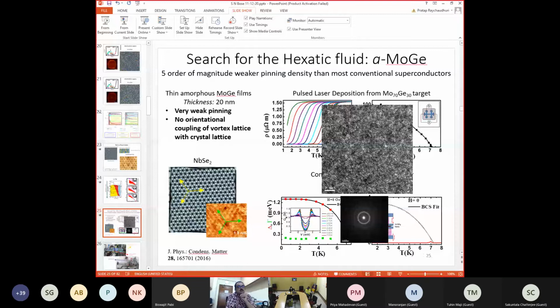You can see the TEM images. It's completely amorphous, featureless, and it has these broad rings, which you also get for an amorphous superconductor. The film that I will be showing the results of today had a thickness of about 20 nanometer. Other than being an amorphous superconductor, because it's amorphous, it does not have any orientation.